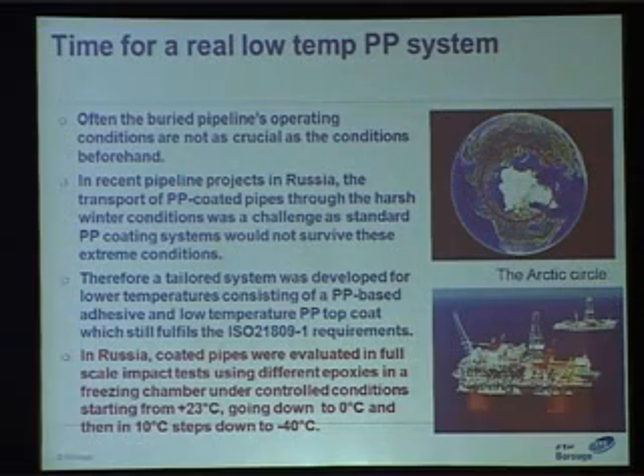In the recent South Stream project, which was one of the major pipeline projects carried out last year, for coaters in Russia, the transportation of PP-coated pipes in the harsh winter condition was a big challenge, as the standard PP systems would not survive. And therefore, a tailored system was developed for lower temperatures, consisting of a low temperature PP adhesive and low temperature PP top coat, which still fulfills ISO requirements.